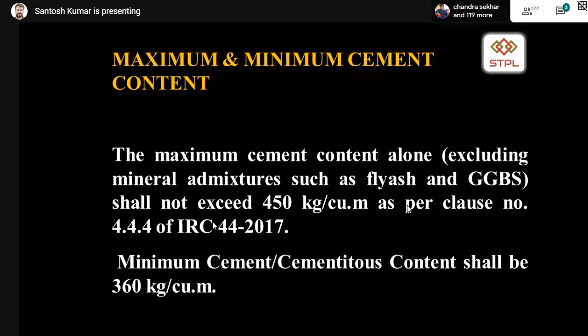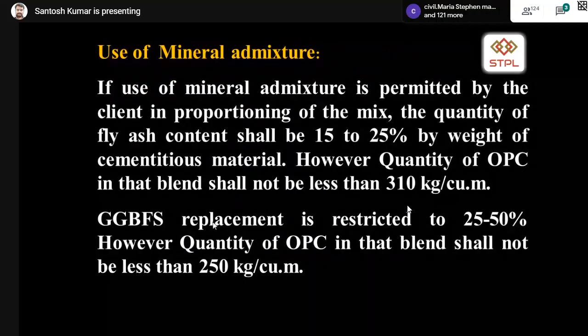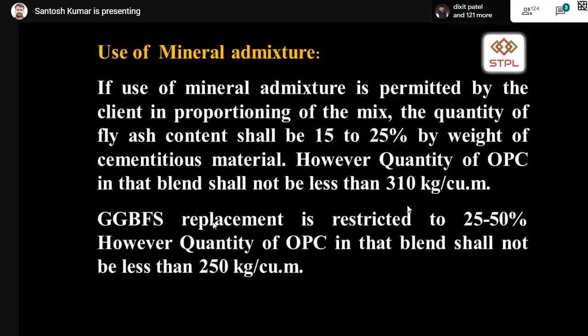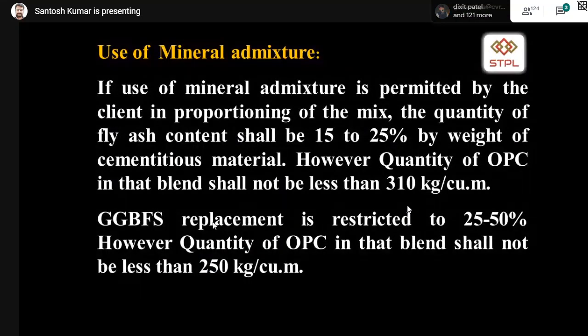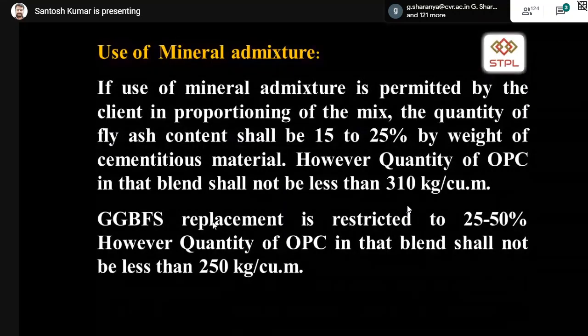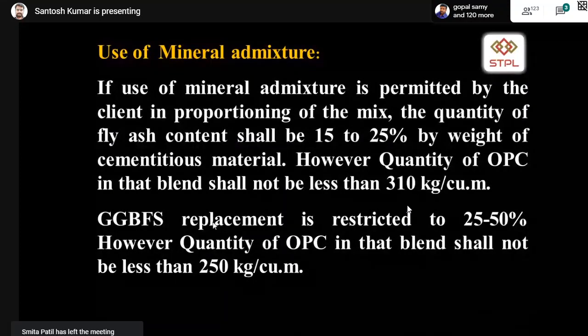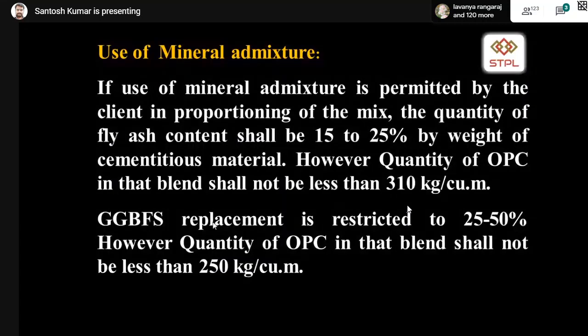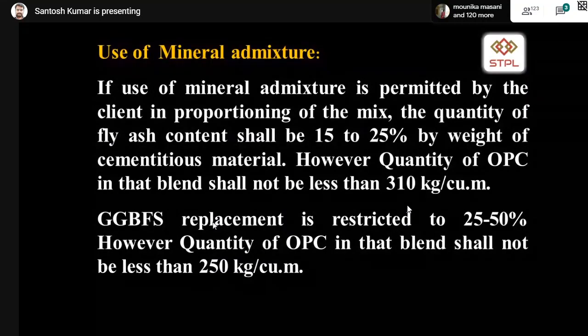Whereas minimum cement content shall not be less than 360 kg when it comes to pavement quality concrete. Use of mineral admixture, we all know it is 25% for fly ash, but when you use it in high strength concrete, you see the lower limit is also given, 15 to 25%. And in that case, minimum pure cement should be 310 OPC. And if you are using GGBS in your high strength concrete, prefer lower dosage of GGBS, 25 to 50 is permissible. And in those cases, minimum pure cement OPC shall be 250 kg per cubic meter.